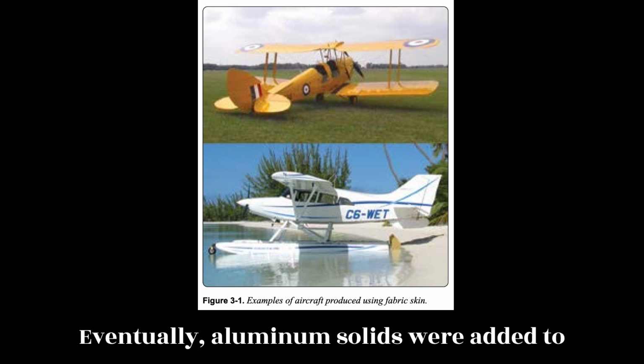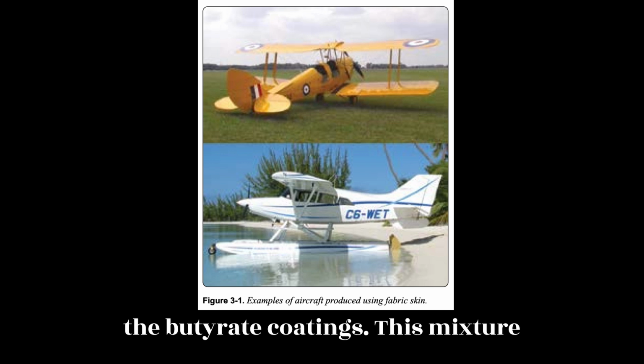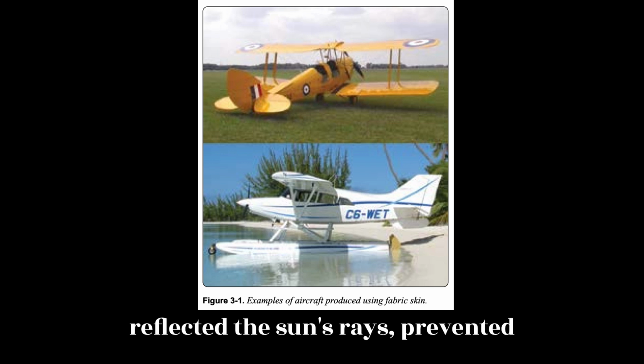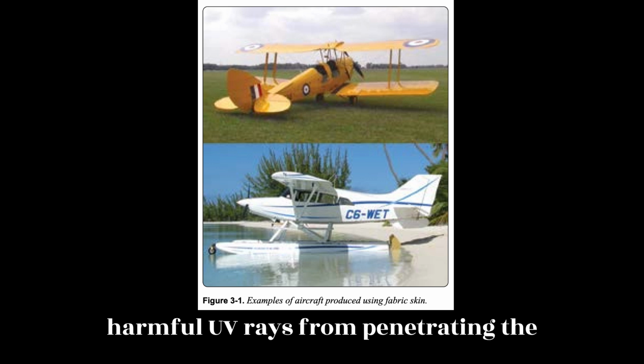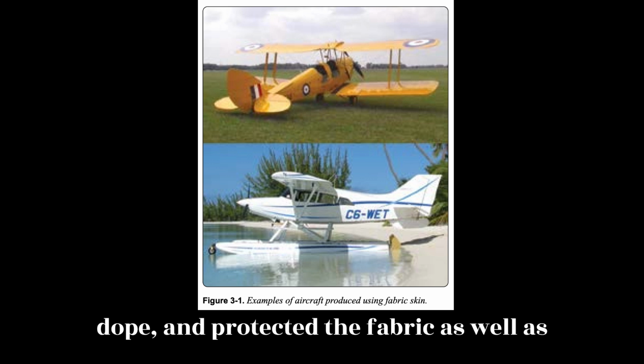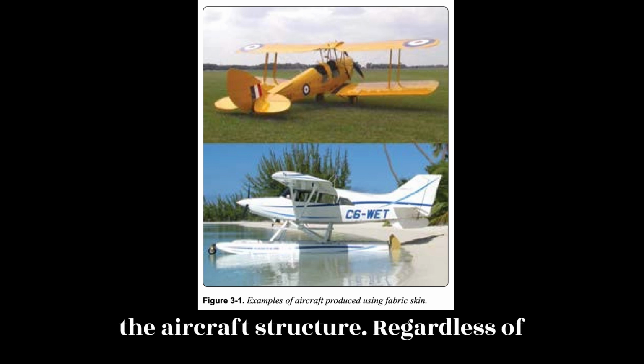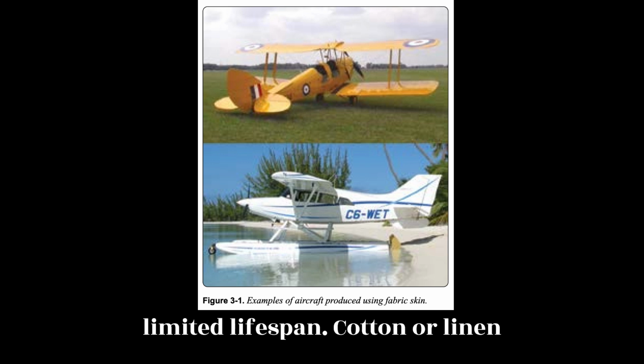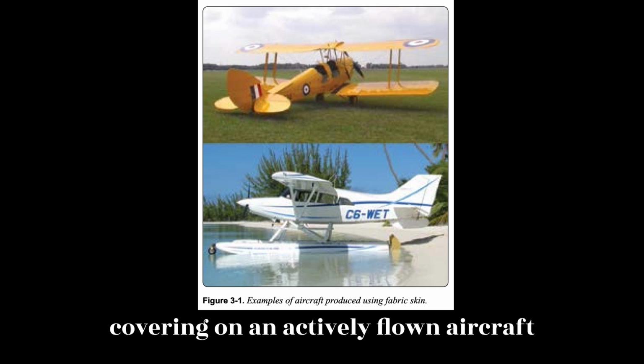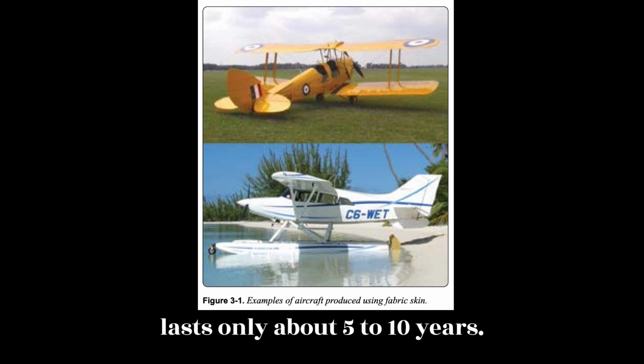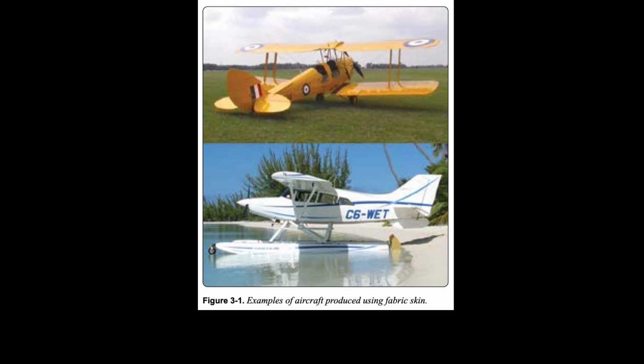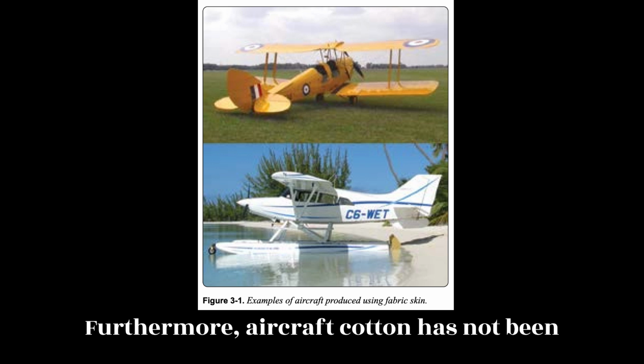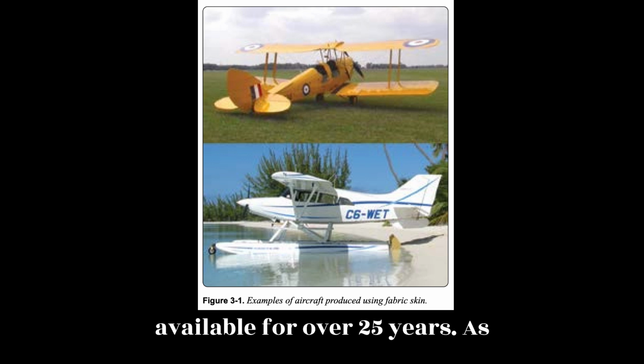Eventually, aluminum solids were added to the butyrate coatings. This mixture reflected the sun's rays, prevented harmful UV rays from penetrating the dope, and protected the fabric, as well as the aircraft structure. Regardless of treatments, organic fabrics have a limited lifespan. Cotton or linen covering on an actively flown aircraft lasts only about 5 to 10 years. Furthermore, aircraft cotton has not been available for over 25 years.